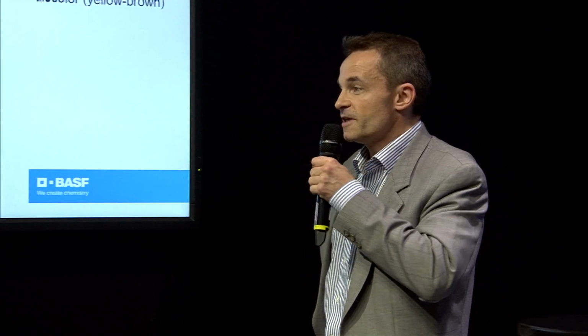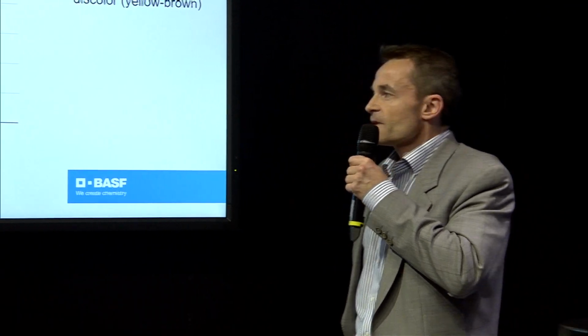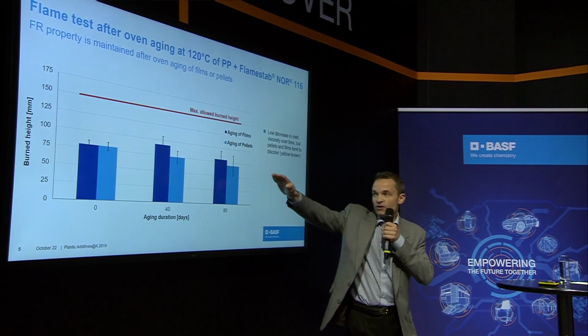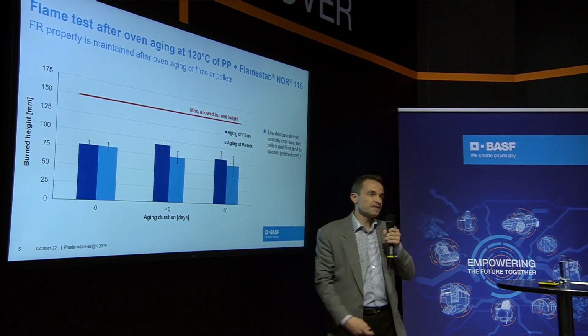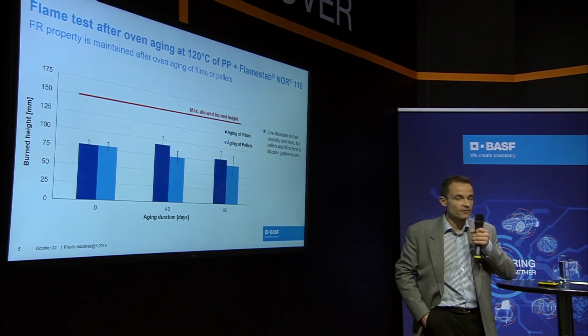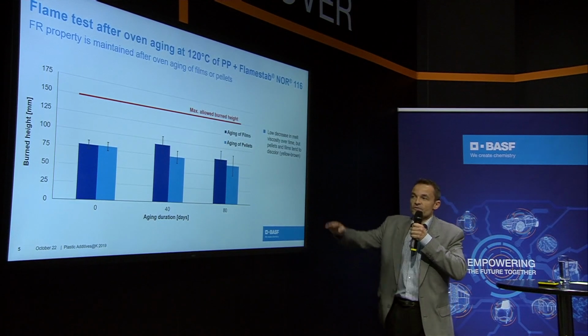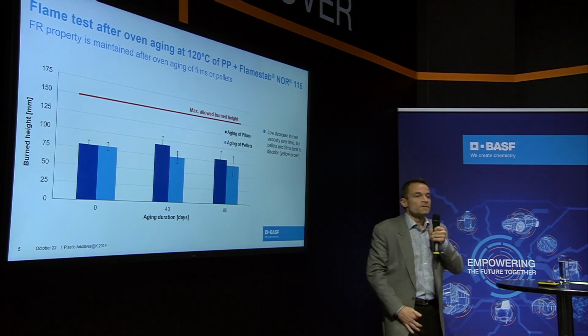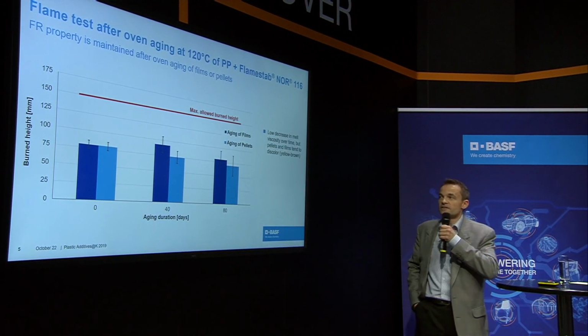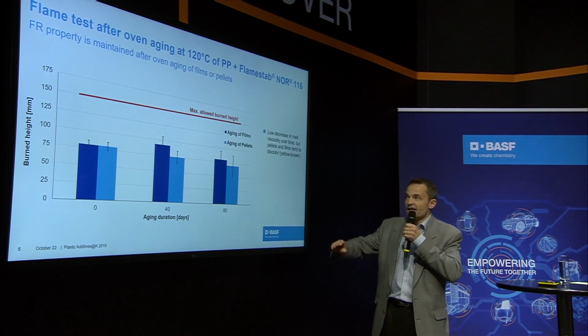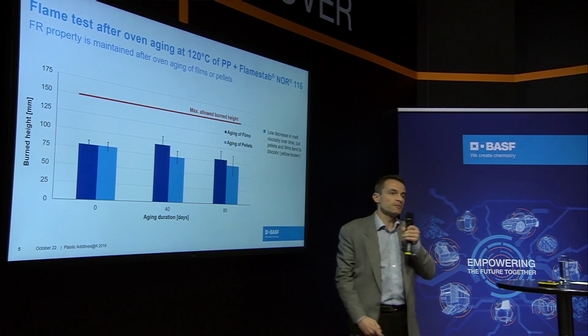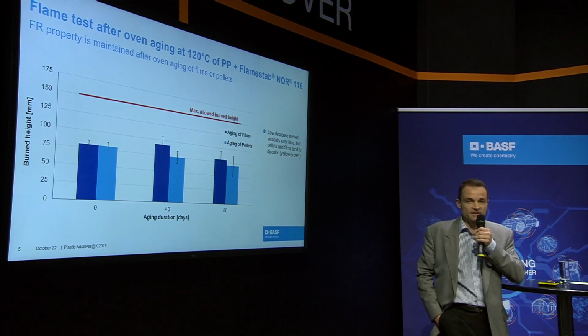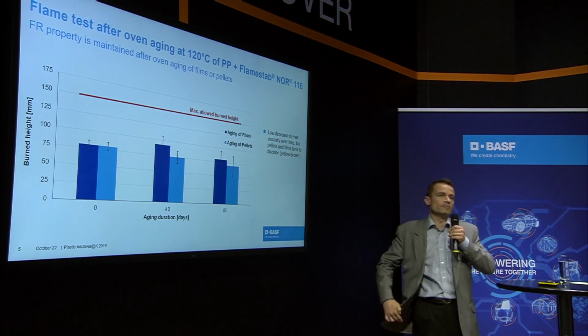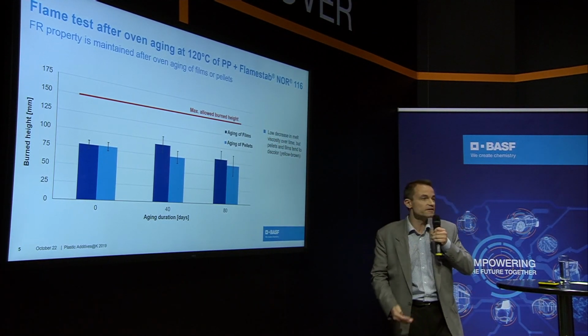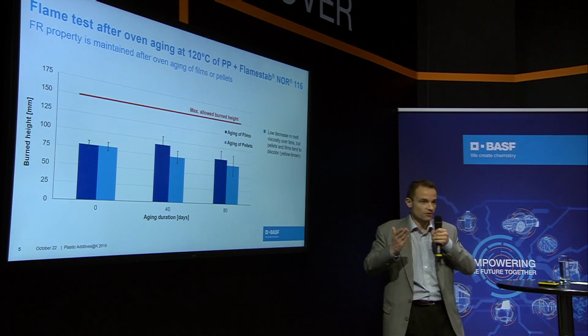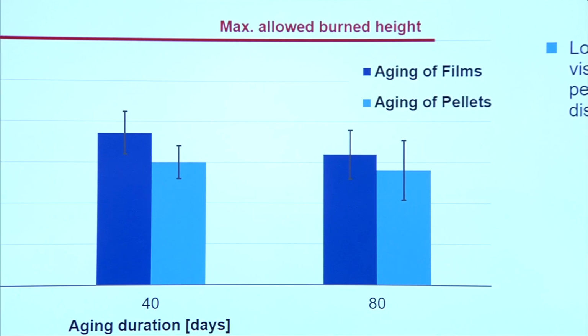Still with polypropylene, now oven aging. You can see for yourself that after 80 days at 120 degrees, which is a lot for polypropylene, there is no change of the flame retardancy, and the performance is nicely maintained, whether the aging took place on the films or on the pellets. In this case also, the melt index tends to increase. A certain yellowing took place after oven aging, which is normal in a way.